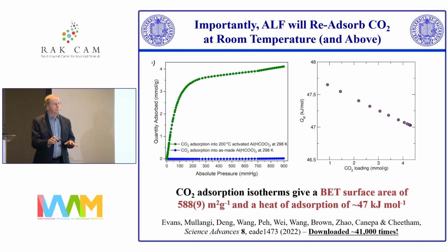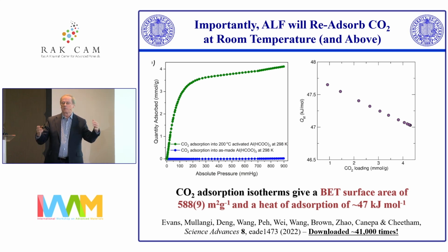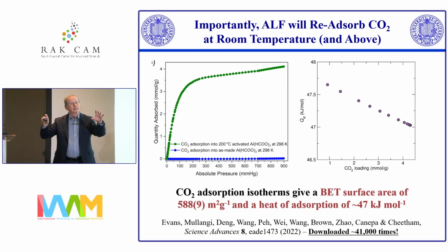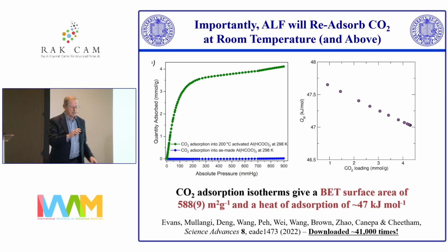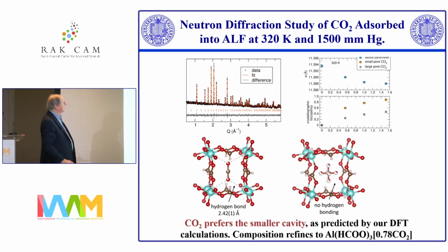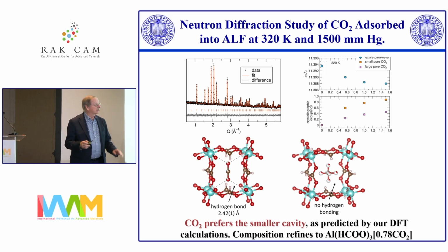So Andy Cooper was talking about a material the other day, which was about 40, and he said that's very high. This is extremely high for CO2 in a MOF-type material or porous material. And that's because the CO2 is hydrogen bonded at each end within the cavity to the hydrogens of the formate linkers. So you get hydrogen bonding between the oxygen of the CO2 and the formate linkers. So we did some very nice neutron diffraction work on this, which was actually done by Hayden Evans at NIST, and sort of beautiful Rietveld refinements.